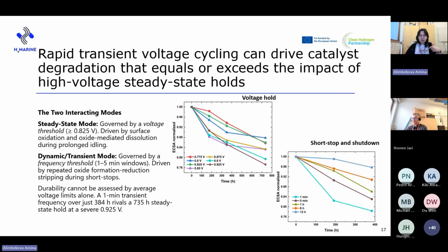Under the dynamic condition, the short stop and shutdown, the frequency threshold emerges at faster timescales at the 1 minute and 5 minute dwell times, where repeated stripping of the oxide layers drives faster dissolution. When the shutdown occurs at larger timescales, the degradation slows down.